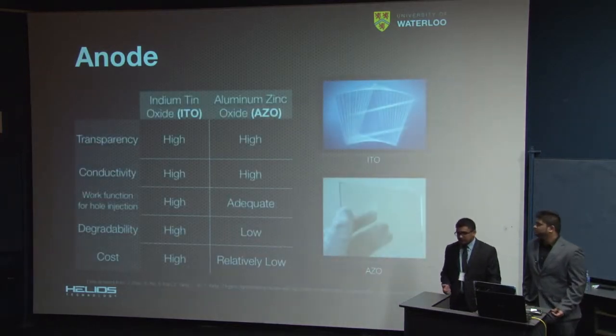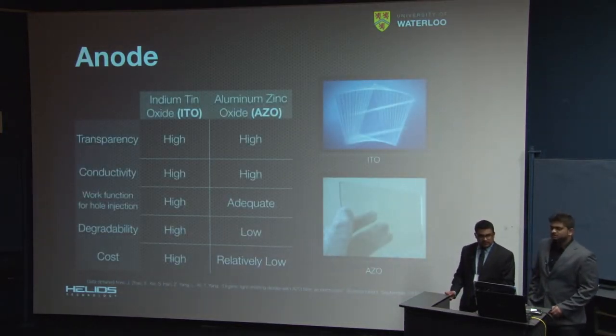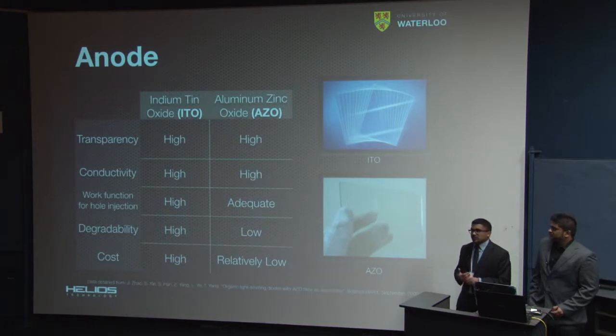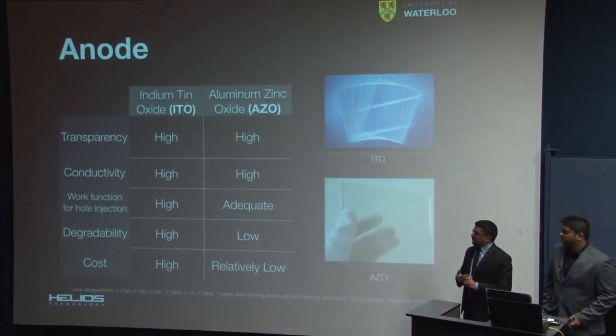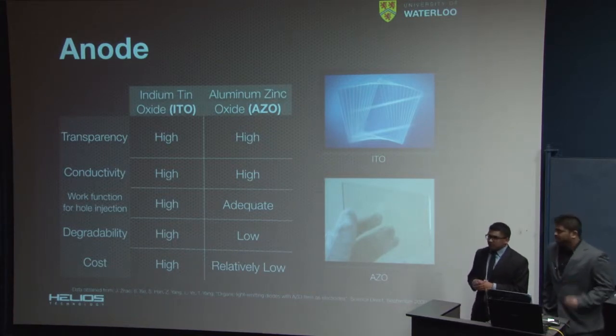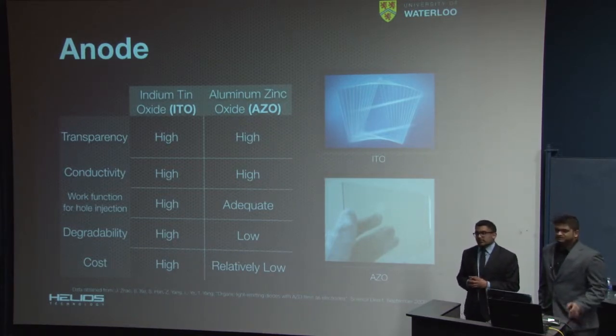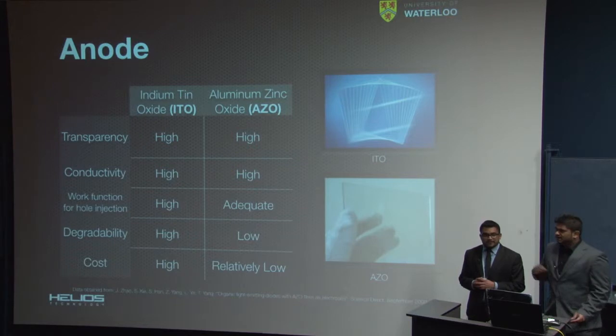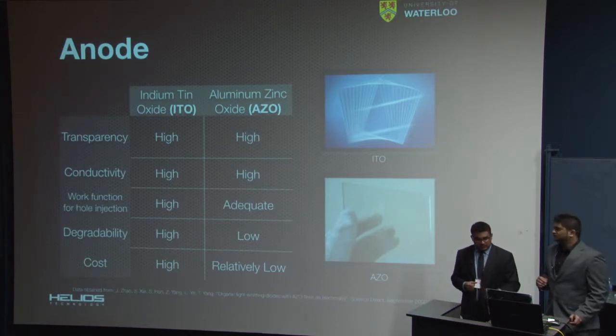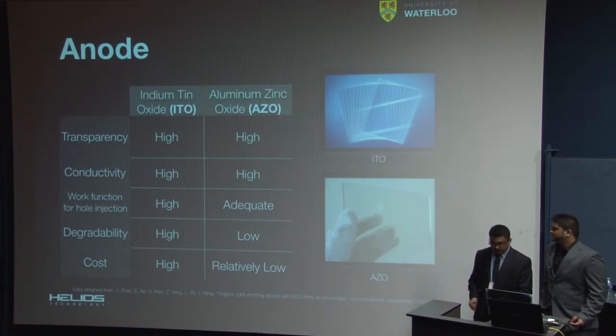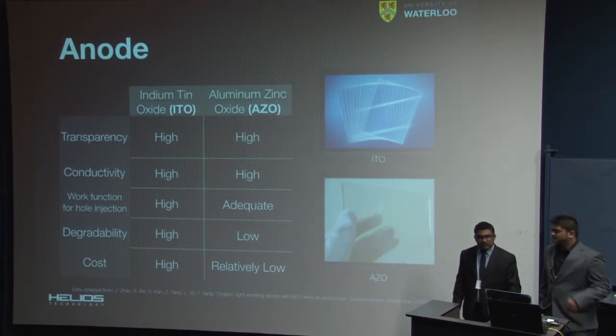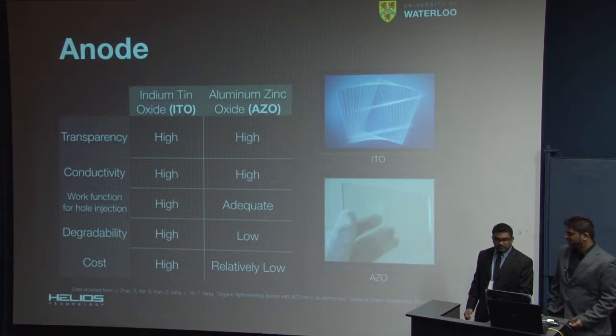For the anode material, we chose to use aluminum zinc oxide over ITO because though both of them offer a good amount of transparency, ITO is known to degrade very much faster. So this ensures that we don't need to do anything extra to ensure that our product isn't degrading, such as nitrogen encapsulation or other such factors, when we transfer the product from one place to the other.